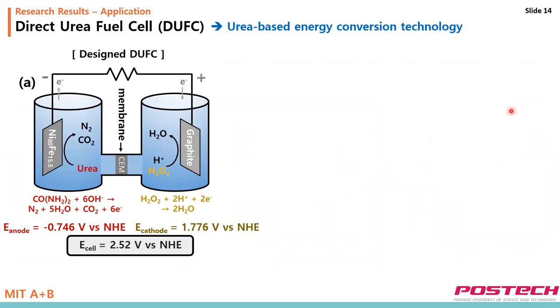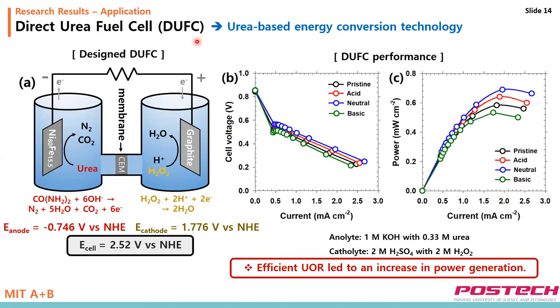In addition, urea oxidation reaction can also be used in a direct urea fuel cell, and the system configuration is as shown in the figure. Thermodynamically, a combination of oxidation and reduction reaction leads to a spontaneous reaction. Direct urea fuel cell makes it possible to generate current without energy supply. So, treated electrodes exhibit the highest power density, which means that efficient UOR leads to an increase in power generation.